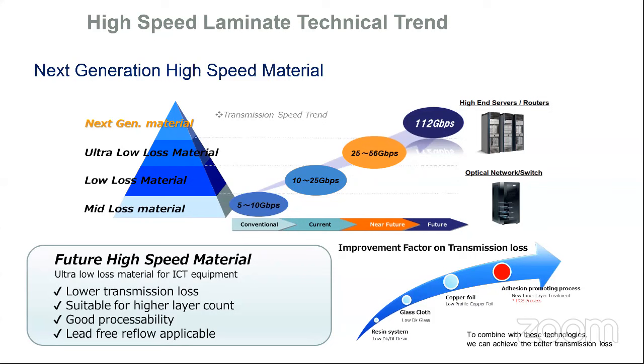Copper foil is certainly getting a lot of attention. Copper foil, certainly low profile, needs to be in order to keep signal loss, insertion loss at a reduced level. And once we establish copper foil and its profile, lower profile, there is a process that we're familiar with called oxide treatment, if you will. It's an adhesion promoting process.